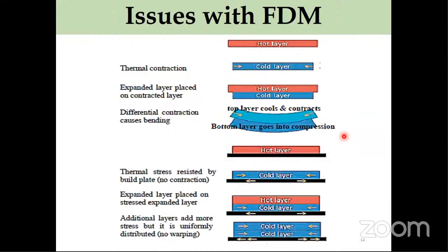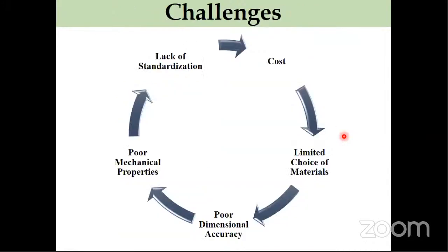There are some challenges also. Say, for example, in a typical FDM process, there is a cold layer on which a hot layer is deposited. And because of this differential temperature, I would say temperature gradient, a stress gets developed, and that actually leads to contraction and may lead to warpage. That is why we have to choose an optimal bed temperature and optimal extruder temperature also, so that the temperature gradient is not that much, and the bonding is perfect. The interbonding strength will actually determine the quality of your part, be it mechanical strength or any other property.